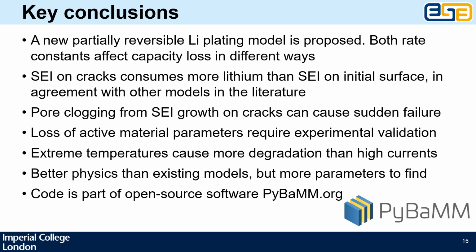What have we learned on our journey through the degradation maze? Well, we proposed a new set of equations for partially reversible lithium plating with 2 rate constants that have different effects on the degradation. SEI on cracks consumes more lithium than SEI on the initial surface, which agrees nicely with other models in the literature.